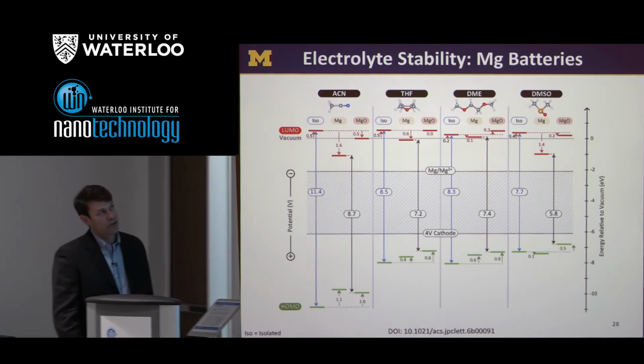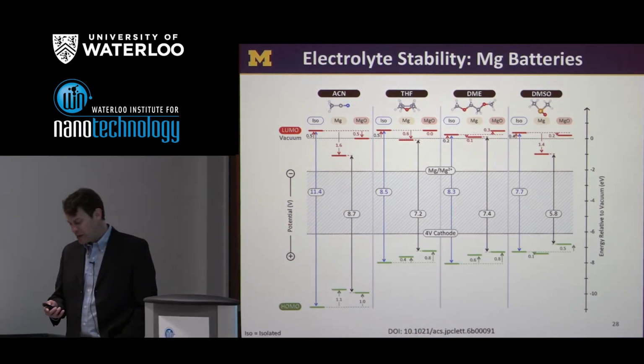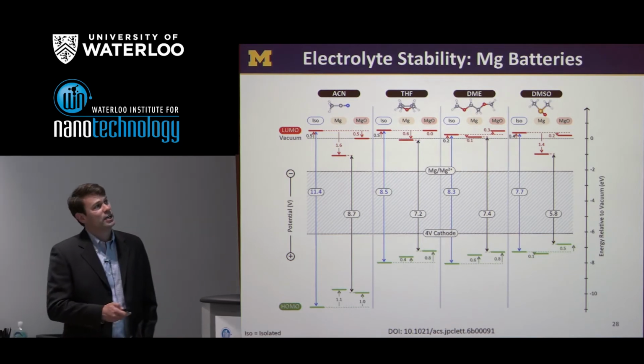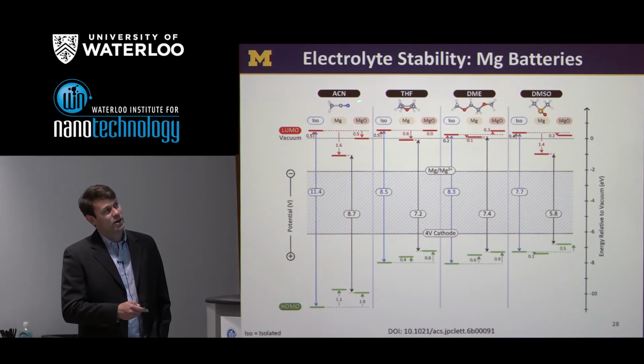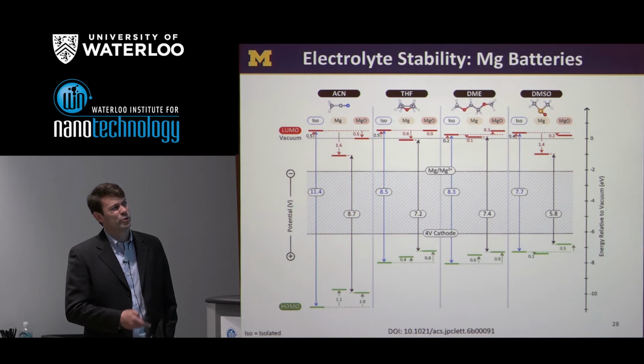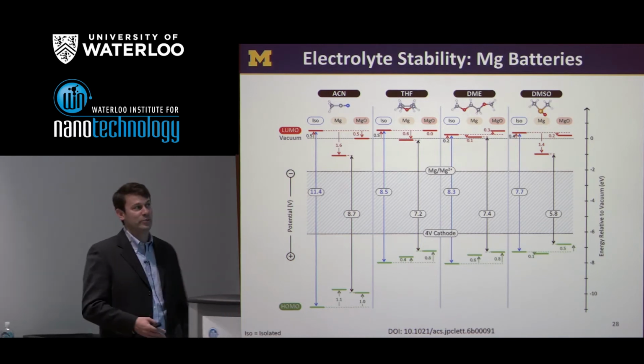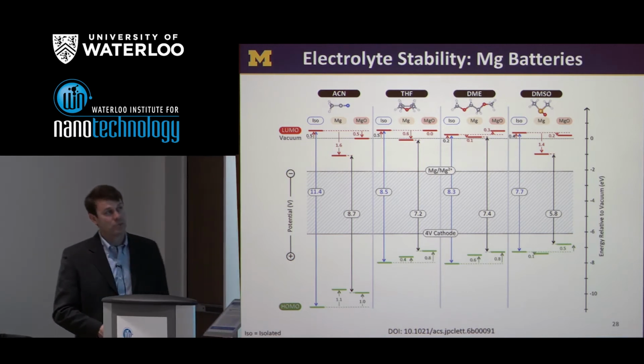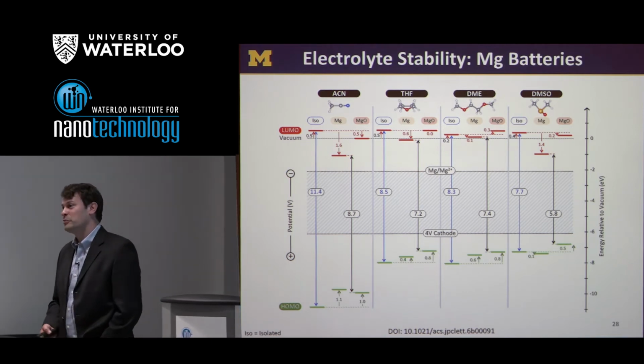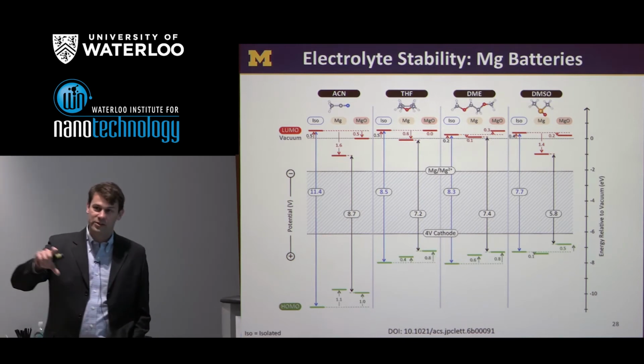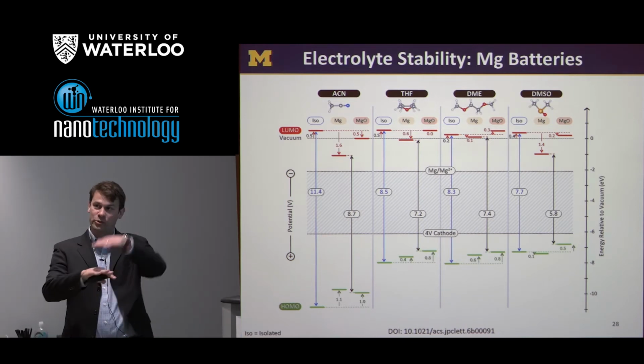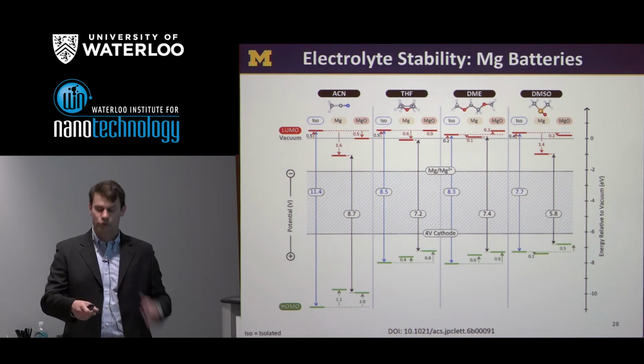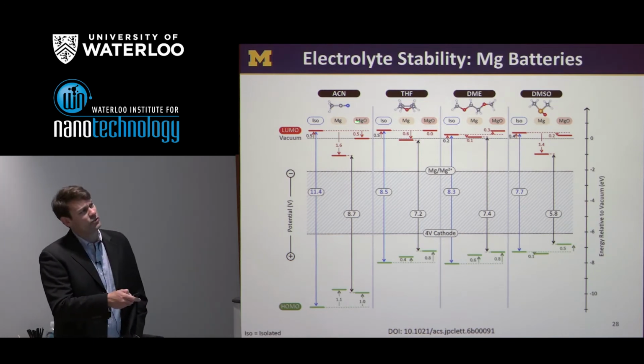So we've done some work along these lines already looking at magnesium batteries, and so this is a bit of a diversion. But to show you what some of our capabilities are, here are 4 common solvents which are used in magnesium-ion batteries. Using GW calculations, we were able to predict, say, the HOMO and LUMO levels of the isolated molecule. Again, that's something which can be routinely done with quantum chemical techniques. Our contribution has been to take those levels and ask how do they change when you take one of these molecules and put it at an interface with an electrode. And that is shown for these 2 columns over here.